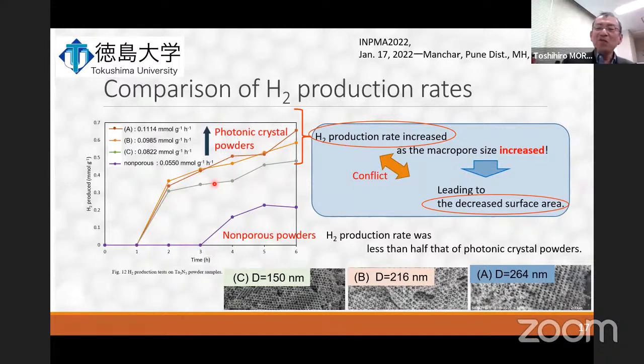Then we move to the comparison of the three photonic crystal powders. Hydrogen production rate increased as the macropore size increased. That means C had the smallest and A had the largest pore size. You remember? C had 150, B had 216, and A had 264 nanometers. Okay, then this is the largest, this is the smallest.